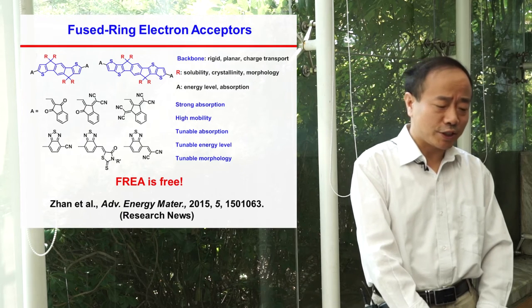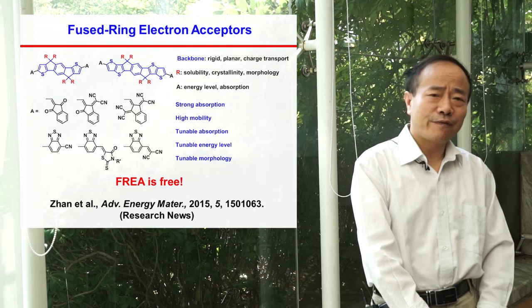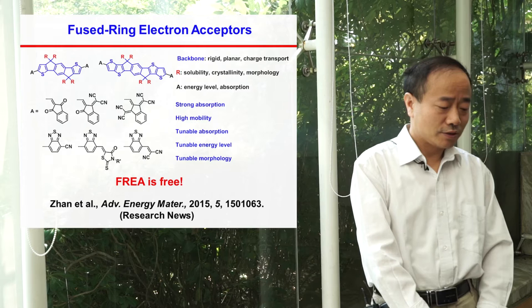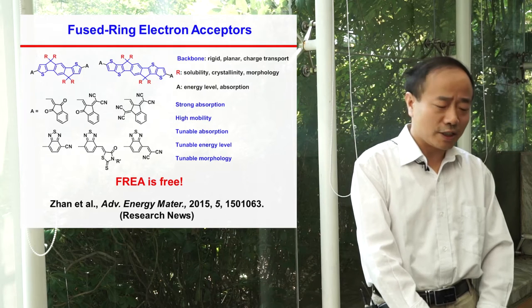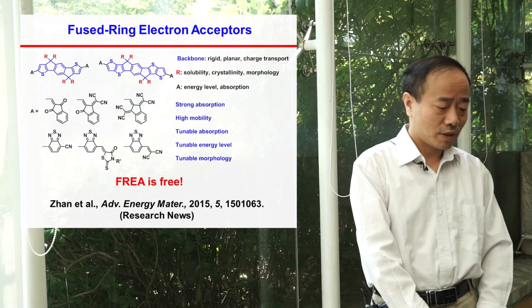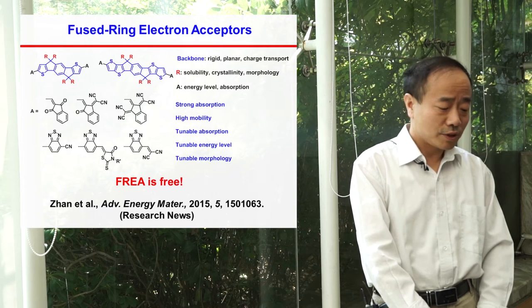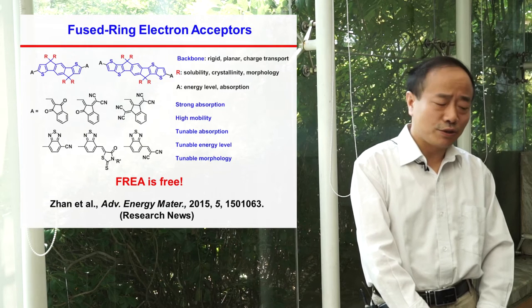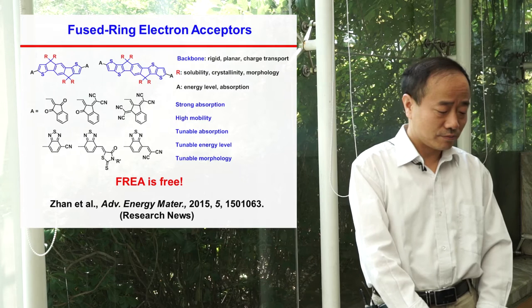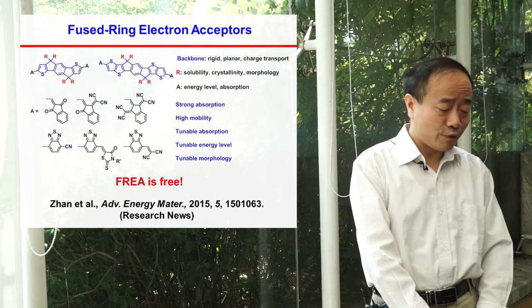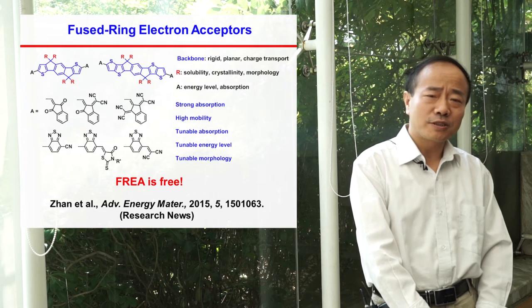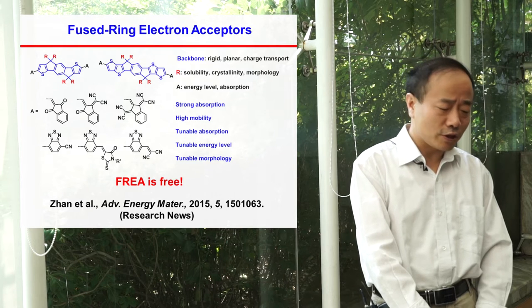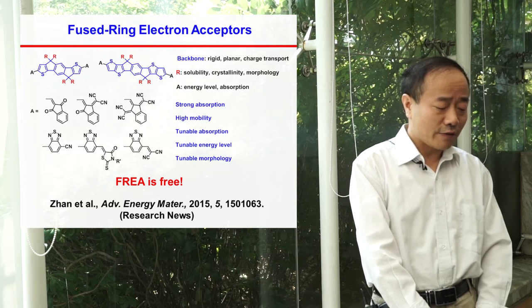We also have different side chains like alkyl, phenyl, thiophene. These side chains can adjust solution processability, crystallinity, and film morphology. Moreover, we have different end group electron-withdrawing units. These units can tune energy level and absorption. So our acceptor is free. That means we can freely tune absorption, tune energy level, tune film morphology, and all these molecules have very strong